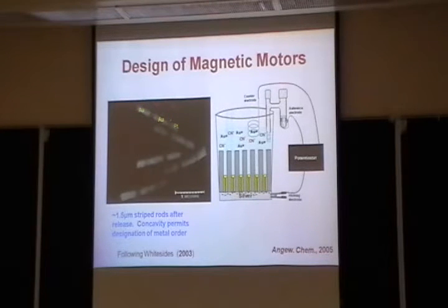Again you make them using these alumina membranes, and you just sequentially electrodeposit these metals and then free them from the membranes, and then you magnetize these little nickel segments, and now you should be able to control them using a magnetic field. So the engine is still hydrogen peroxide decomposition, but the magnetic field helps them orient.